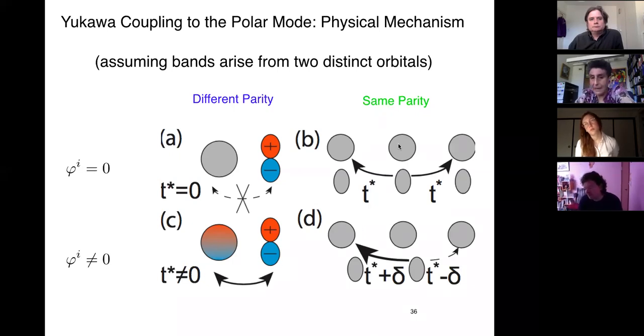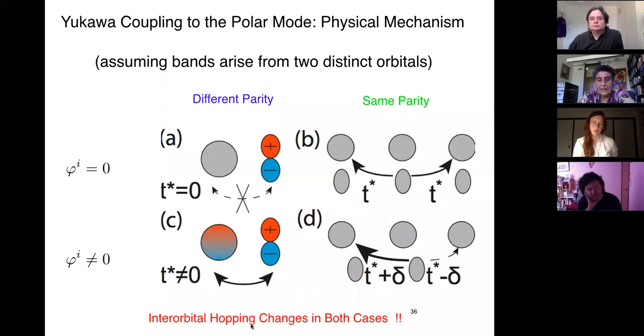If we have the same parity, then momentum dependence is necessary. We can't view this locally. However, inversion symmetry breaking means that interband hopping to the left is going to be different than interband hopping to the right, a little bit like dimerization in the Su-Schrieffer-Heeger model. And in both cases, the interorbital hopping changes with the inversion symmetry breaking. So that's a sort of simple cartoon of how this can work.